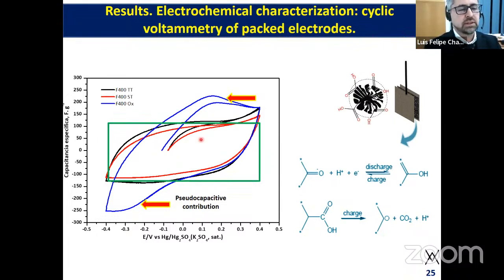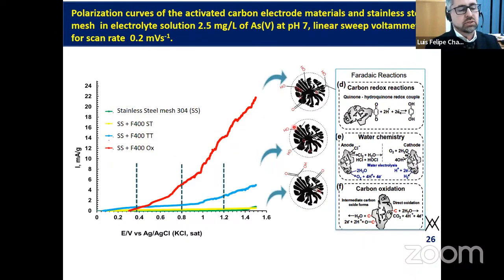And what is the origin of these secondary reactions? This material has a considerable amount of oxygenated groups, which are susceptible to reversible oxidation or reduction reactions, which are shown here. But these reactions are considered parasitic; they affect the performance of the electroadsorption. This is consistent with this polarization profile, the red one. In this case, you can see that the more acidic material oxidizes at lower overpotentials than the other materials, which gives it a disadvantage for electroadsorption.